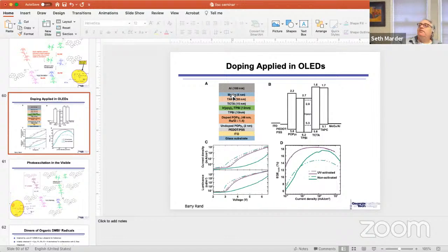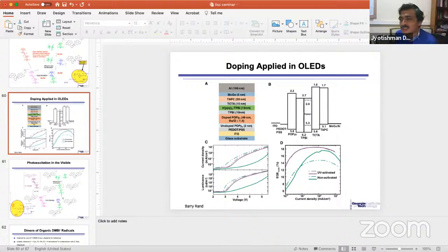Let me make one last comment. I would say that people have talked about using doping in OPV systems to modulate conductivity and things like that. I would be mindful that if you tried to dope the active layer of an OPV, that polaron quenching of excitons could well be a problem, and I think that that's something that people have been very mindful of. Yes, it does affect. Seth, I think there are papers which seem to be controversial in that regard. Yep, I agree.